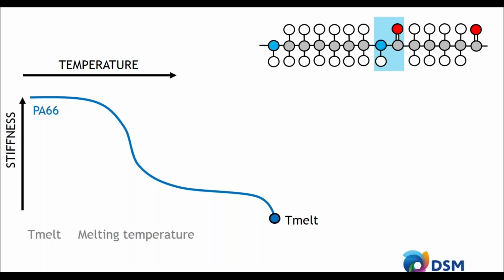The first one is, of course, the melt temperature. The melt temperature for a polyamide 6,6 is somewhere around 255 degrees C. That means if you reach peak temperatures above that, you will end up with a very fluid polymer, and this material cannot be used. You have the crystallization temperature, also very important, because below that your material gets its structural integrity.